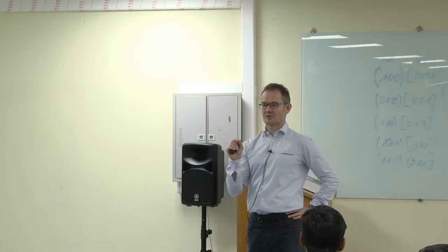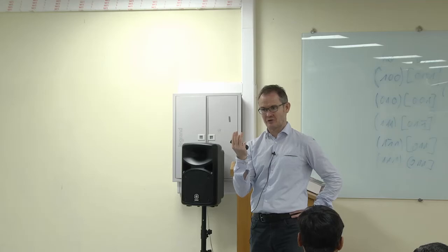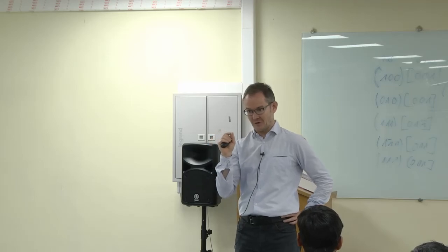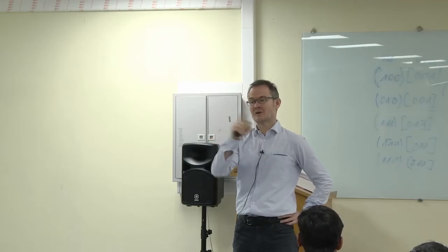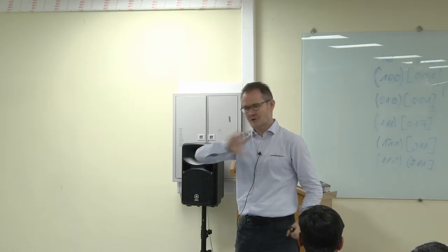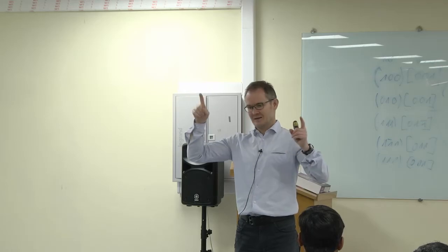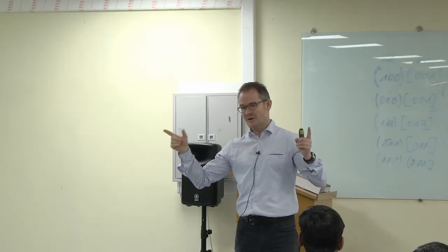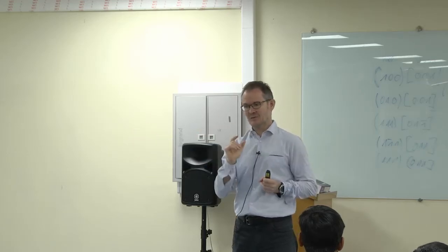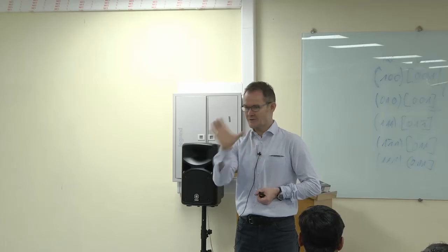When you work with quaternions, it is just a fundamental mathematical set of rules. It doesn't know anything about symmetries. So you have to bring in the symmetry yourself first. And that is indeed important. The set of quaternions is very simple to write. You need just a few lines of code, you have your quaternions. But then you need more lines of code to consider that the quaternion for 001, 110 is different from the quaternion for 100, 011. Although quaternions are easy, you still have to deal with the symmetry yourself. You have to write the code.